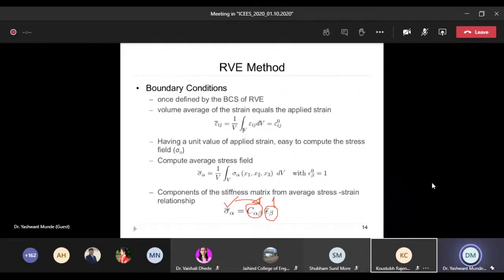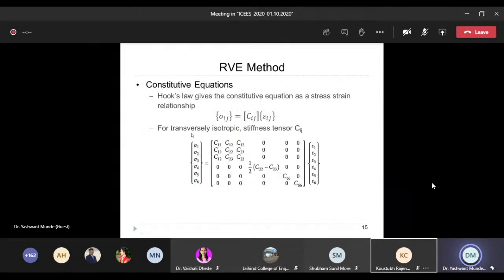And once you calculate the CIJ matrix, for example, if you have a transversely isotropic material, there are only a certain number of CIJ constants you need to calculate. So how many are there? C11, C22, C12, C23, and C66. So 5 constants you require to calculate. And once you know these 5 constants of the stiffness tensor, then we can easily calculate the elastic properties.